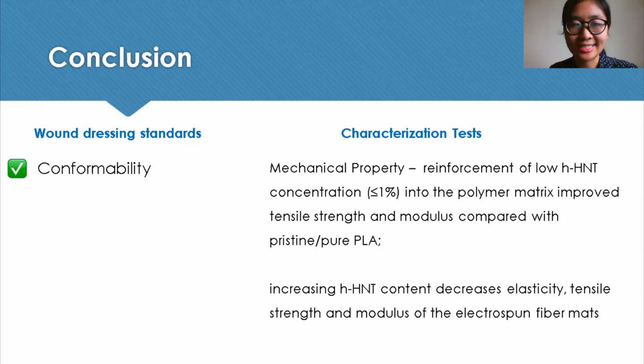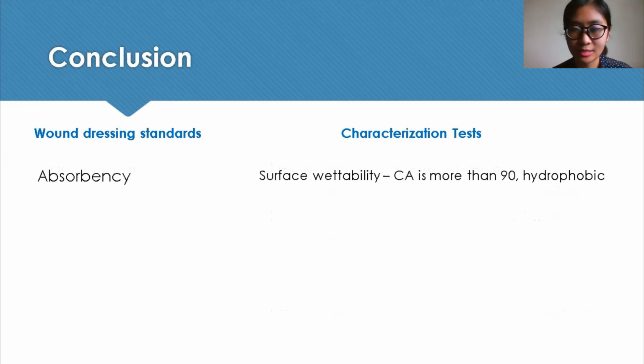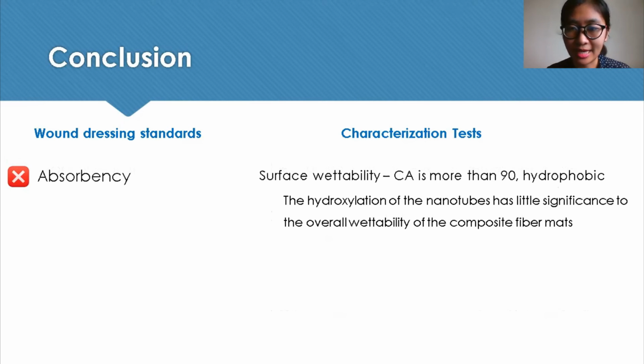However, increasing HHNT content further decreases the elasticity of the fiber mat, which may hinder the conformability of the material when applied to the wound surface subject to movement. Okay? As for the material surface wettability, its contact angle is more than 90 degrees, so the material is hydrophobic. So it does not address the absorbency property of a wound dressing. It was also concluded that the hydroxylation of the nanotubes has little significance to the overall wettability of the composite fiber mats. However, the waterproofness property of a dressing can be addressed if the fabricated material is used as an outer layer in contact with the environment, protecting the wound from foreign liquids. So it can be for waterproofness.